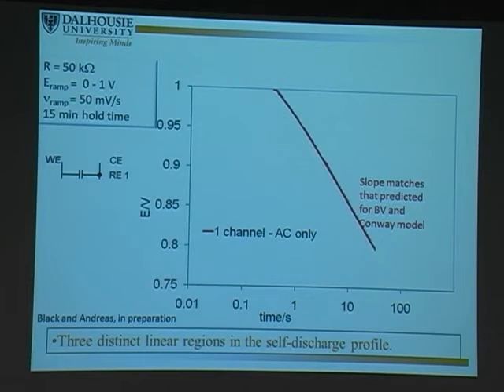And so we did, first of all, we tried it with just one capacitor in the system, and we get exactly the profile we expect. The plateau was a little above one here, so you can't see it very easily, but we have a linear drop in potential, and the slope that we calculate from this exactly matches what we expect. So everything's working properly here.